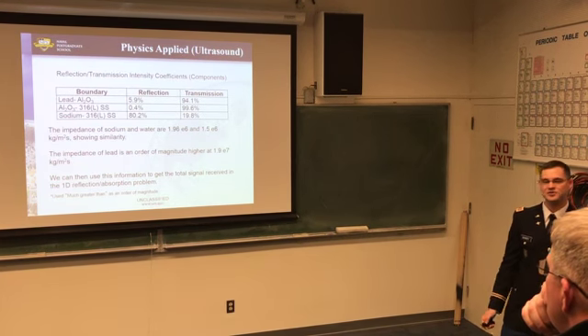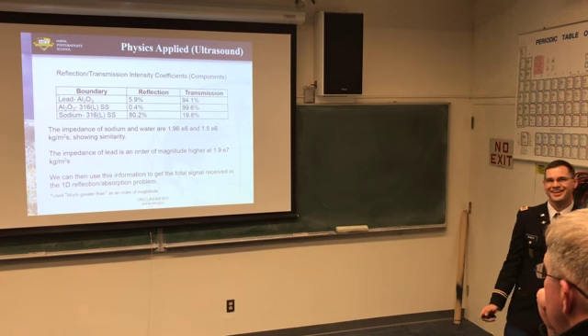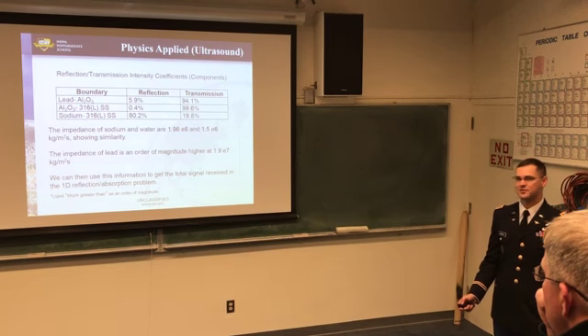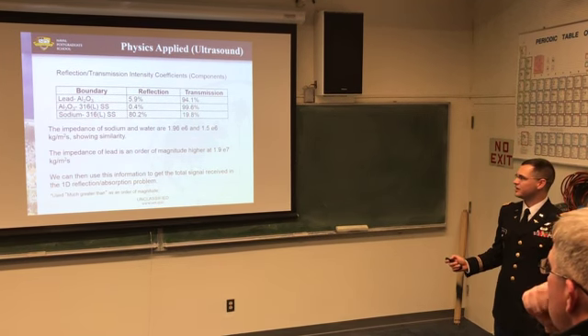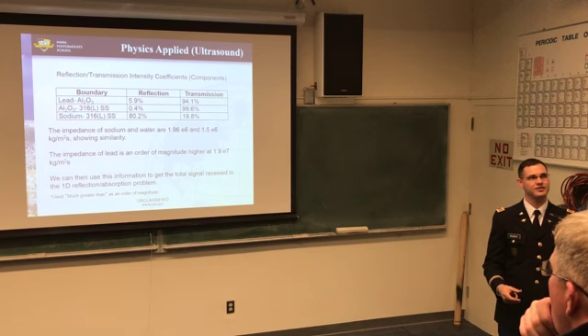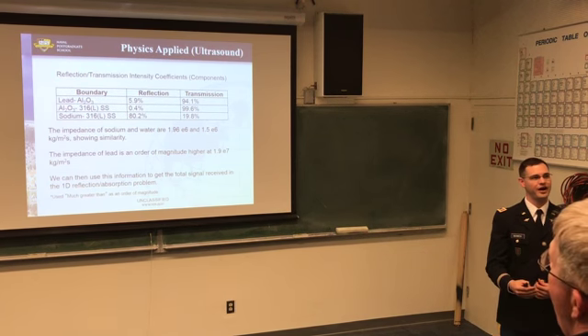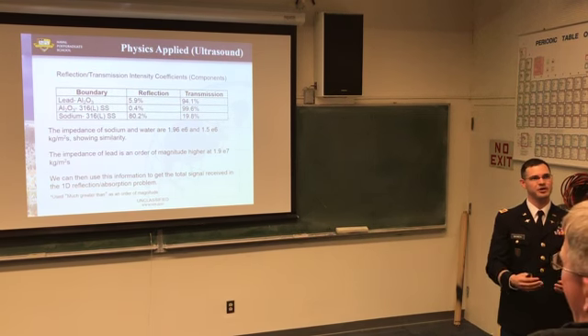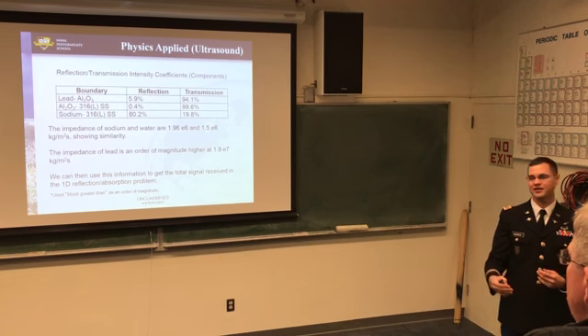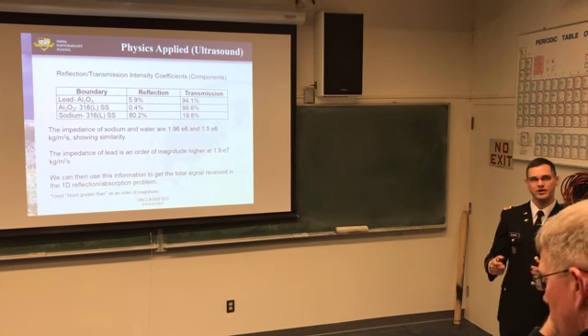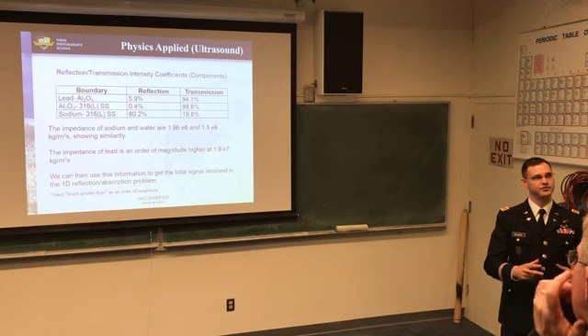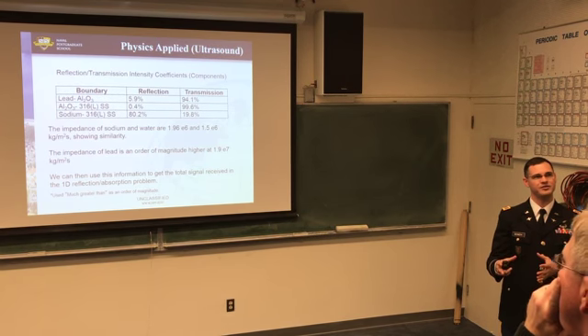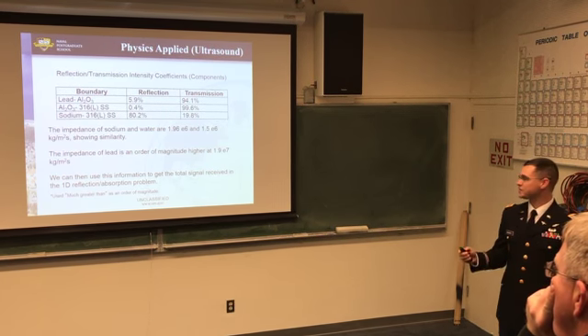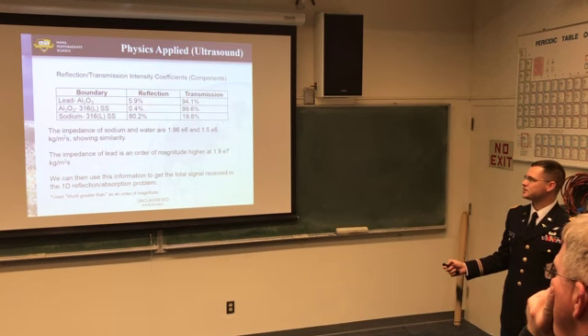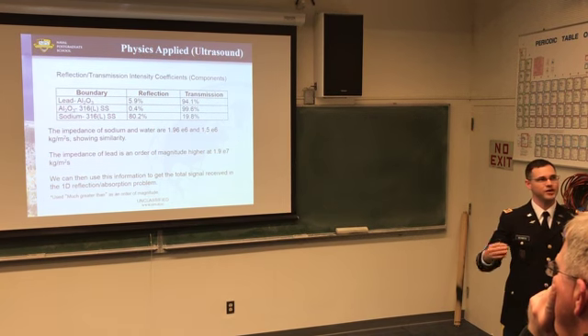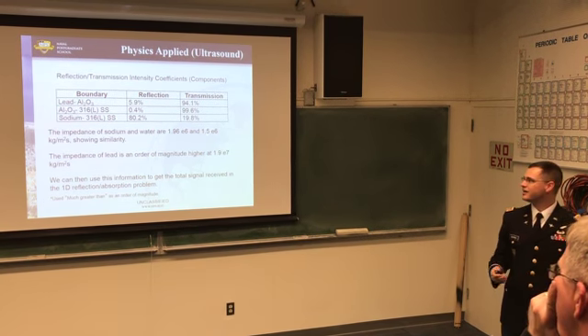Last thing we looked at was the reflection transmission intensity coefficients, and this is where we ran into some interesting results. So lead is extremely dense, so therefore it has a very high acoustic impedance, which is the density times speed of sound. And because of that, molten lead is very comparable to all of our components inside the reactor vessel. So you actually get a very small reflection, about 6%, when it bounces off the components and comes back.